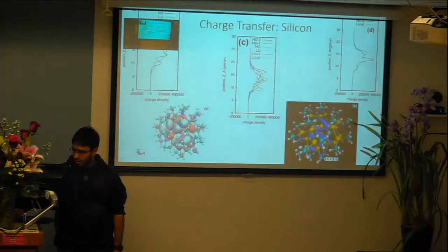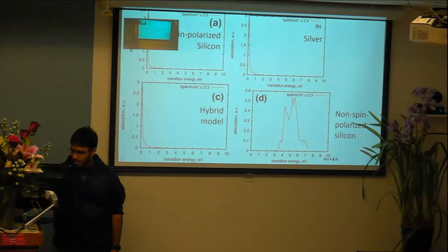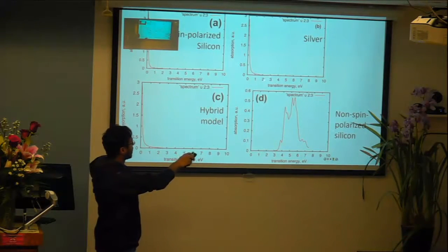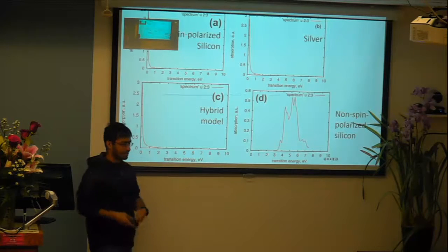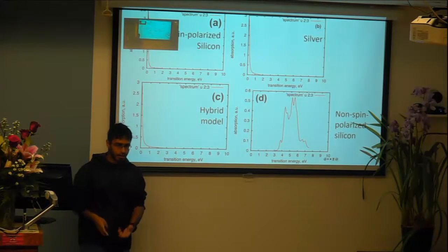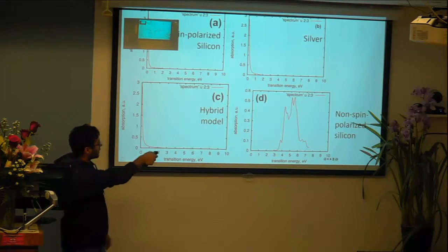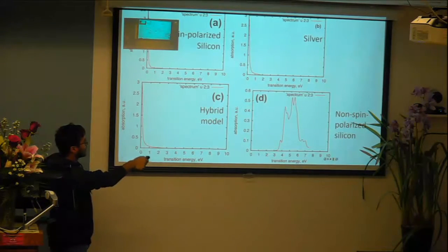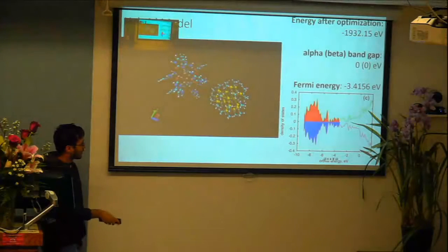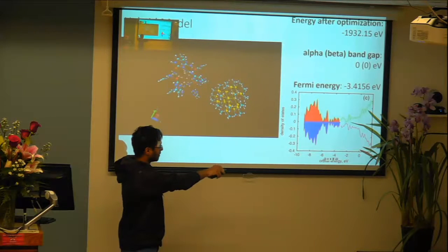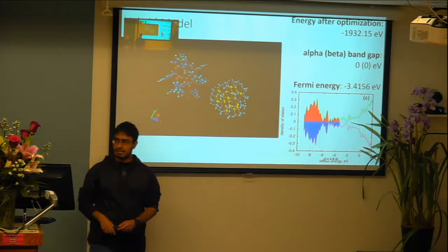Yeah, so I'll go back to the plots, yeah, right here. So the question was what the significance is of this absorption spectra basically having a peak at zero, how it could be removed, and if it's real or not. So the peaks near zero, right here in the spectra, were actually a consequence of having the HOMO and LUMO states be very close to each other.